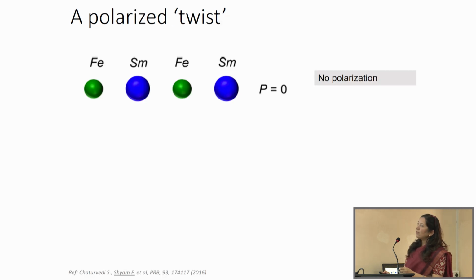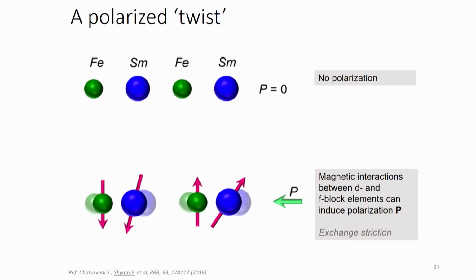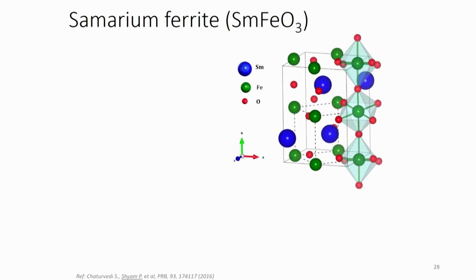So here we have worked on samarium orthoferrite, SmFeO3. We picked samarium and investigated it, and finally we found that there is a twist in polarization. I have named it a little to make it interesting. There is no twist, we just found that there was exchange striction, so there is magnetic interaction between D and F block elements and they induce the polarization. So they have induced the polarization in samarium orthoferrite, and we further investigated.